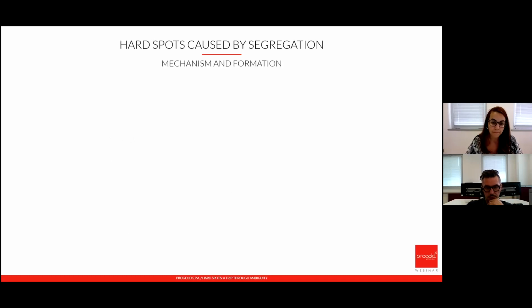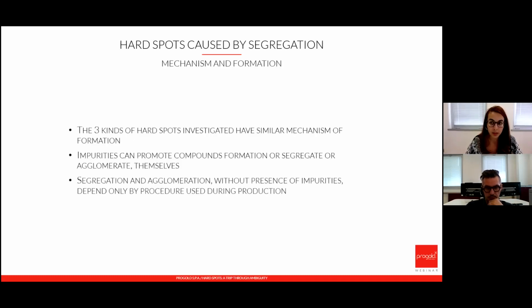So also in this case, similar to the first one, we have the solid material already inside a melt, because it usually comes from whatever is inside the material, and it's not melting during the production of the jewels. They tend to agglomerate, to go together, and at some point they segregate from the phase they're in because they're not soluble in the melt.